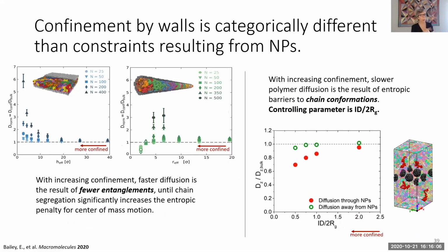So we can put those 2 ideas on the same slide here. In the rigid confinement, we're losing entanglements because of the distortion of the chain conformation, so things get faster, until this funny thing happens in the cylinders where things have segregated. But with the increase in confinement here, going to a smaller and smaller interparticle distance, we're getting more and more confined, and we're actually getting a decrease in the diffusion coefficient, right? This is because there are entropic penalties to squeeze into those little tight spaces. So in that way, the monolayer is behaving a little bit like the segregated cylindrical system. And the other thing that's important to note here is that this interparticle distance relative to the RG is a very critical parameter. That's how much the polymer chain has to distort to get in there.